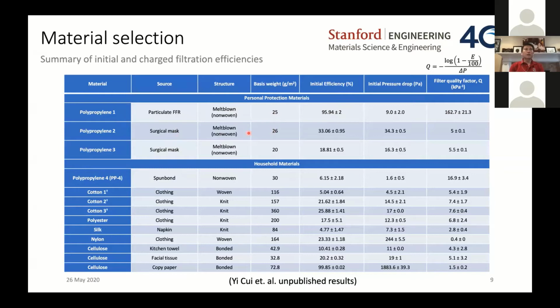And it also uses the melt-blown inside, but its filtration efficiency is low. It's not 95, 96% anymore. It's 33%. The other one close to 20%. Air pressure drop is here, 16 Pa, 34 Pa. This quality factor dropped to about 5 also.